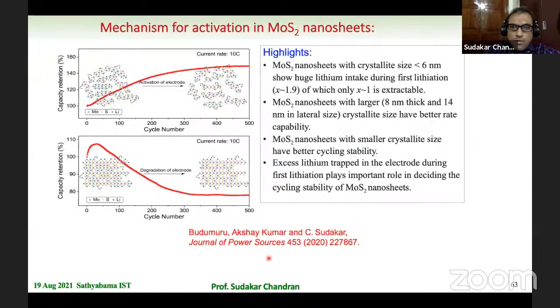So the basic thing is, the extra lithium that gets trapped at the defect sites is what helps in easy diffusion of the lithium, especially in the defect rich samples. The cyclic stability is much better there, whereas in the defect suppressed sample, the rate capability is much better. So we need an optimized condition to get the best of both, and that's where around 800 degree annealed samples are pretty good. You can go through these papers if you want more details.